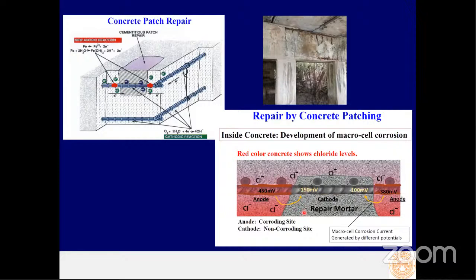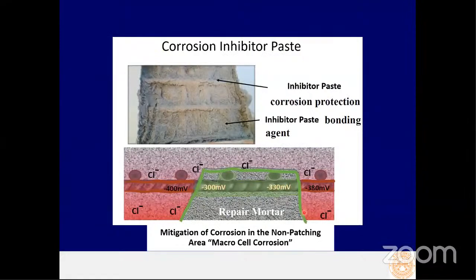So today we are thinking about using a better repair method. For example, we plan to use corrosion inhibitor paste. We try to use this in the repair of minor and medium span length bridges, because usually in that type of bridge, we find corrosion that breaks and delaminates the concrete. So usually we would like to repair the delaminated concrete with some special chemical product that can help us mitigate corrosion in the future. This type of inhibitor paste is going to repair the regular concrete, and we do just a simple patching into the damaged area, and that is going to help us give a longer life for small and medium bridge repair.